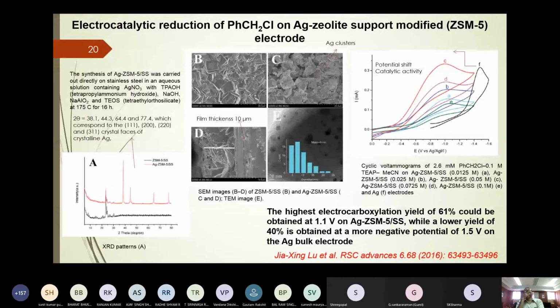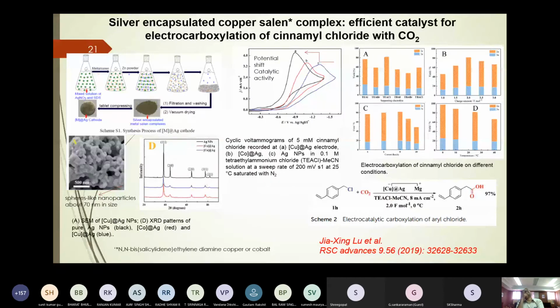Okay. Next slide shows silver nanoparticles put in a copper salen complex. For example, silver nanoparticles can be put in sodium dodecyl sulfate. Then we do methods like catalytic reduction using zinc powder, filtering, washing, and vacuum drying. There we get silver nanoparticles on the salen complex, which we can make in the form of a cell. SEM shows the shape of the silver nanoparticles, which are spherical, with a size of 70 nanometers. And XRD proves the formation of silver nanoparticles on the salen.